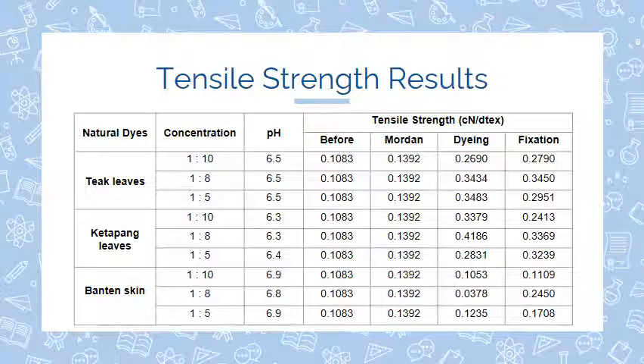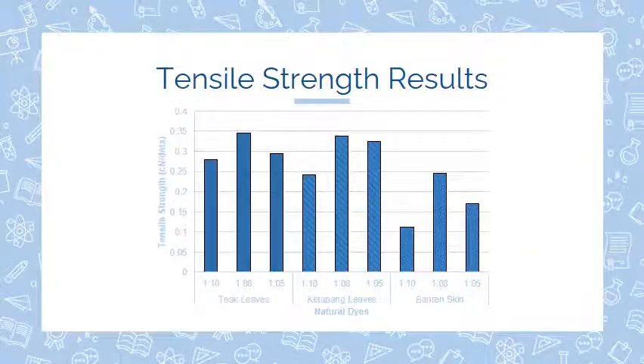A solution with a concentration ratio of 1/8 produces optimal tensile strength, namely 0.34 on teak leaves, 0.33 on ketapang leaves, and 0.24 on Banten skin. From the tensile strength result, we can see that the highest tensile strength occurs in thread colored using teak leaves.